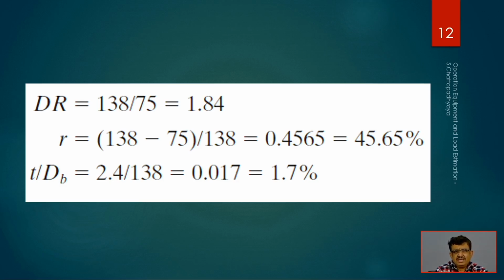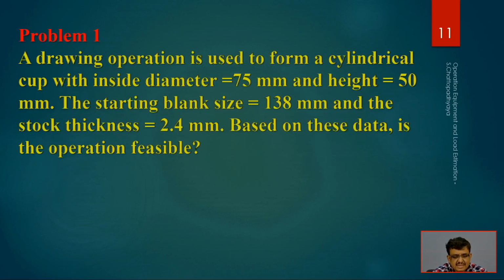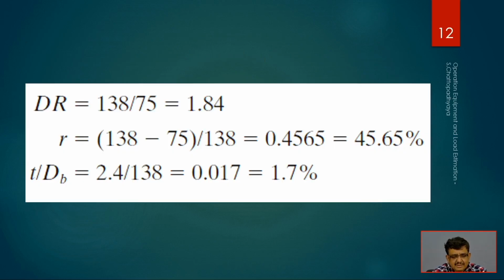That is 138 by 75, and that is 1.84. What is the change? 138 minus 75, that has to be reduced. So 138 minus 75 divided by 138 comes out to be 45.65%. So that is the drawing ratio. And T by DB, that is the third ratio, which is important, where the thickness is 2.4 and the starting blank size is 138 millimeter. So that ratio comes out to be 1.7%.